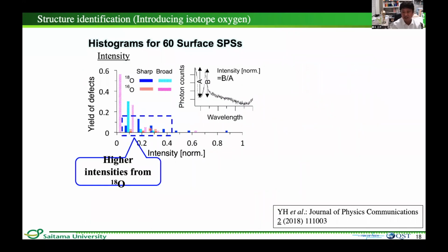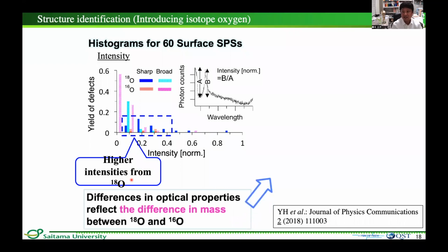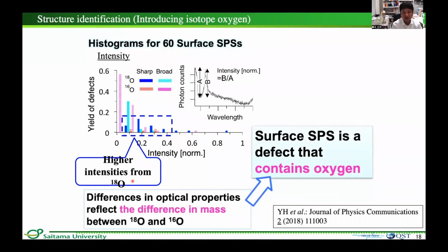This figure is histograms on PL intensity, which shows higher intensity SPS seen from the 18 oxygen sample. From these results, we can say that the difference in optical properties reflects the difference in mass between 18 oxygen and 16 oxygen. So the surface SPS is a defect that contains oxygen.